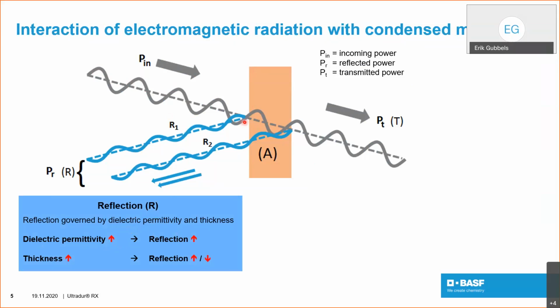If we stick to the point of reflection for a second, the reflection is also governed by the thickness of the material. As you can see, the second step in a dielectric permittivity change between the material and air is at the backside of the material, so also part of the radiation is reflected from this end. And obviously, the scheme is simplified for this moment. The thickness can have both directions. Increasing the thickness of your material can lead to high reflection or lower reflection, depending on if it's a constructive or destructive interference. And I will come to that on the next slide.